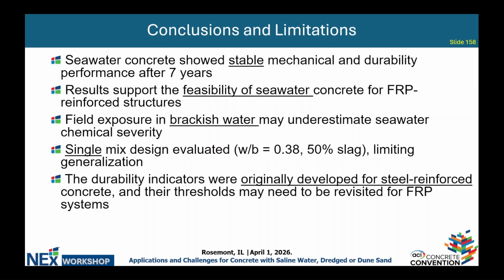However, we have main limitations. The first one is that we have single parameters, including one replacement level of slag as well as a single water to binder ratio, which can limit the generalization of this study. Also, do you remember that we talked about the external water, which is brackish water, which can underestimate the exposure to full ocean water. Finally, we used durability indicators like bulk resistivity to indirectly indicate the chemical resistance of this system. However, they were originally developed for steel reinforced concrete structures, so it may be beneficial to revisit those thresholds to update them for FRP reinforced seawater concrete structures.